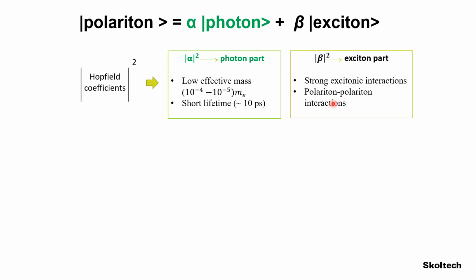But practically what we get from the photon part, we have now quasi-particles which have very low effective mass, as you can see here, orders of magnitude smaller than the effective mass of the electron inside the semiconductor. And we also get, due to the photonic part, a short lifetime. Even if we have very high quality factor cavities, the lifetime is approximately 10 to 50 picoseconds. These are several thousands of bouncings of the photon inside the cavity before it leaks outside.